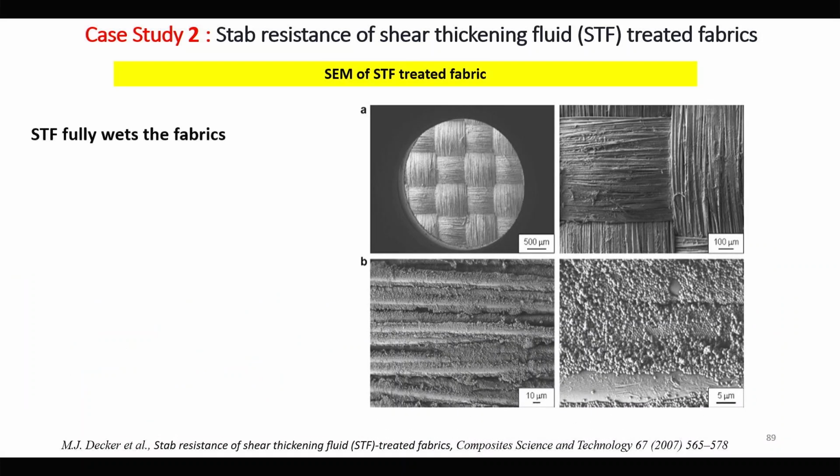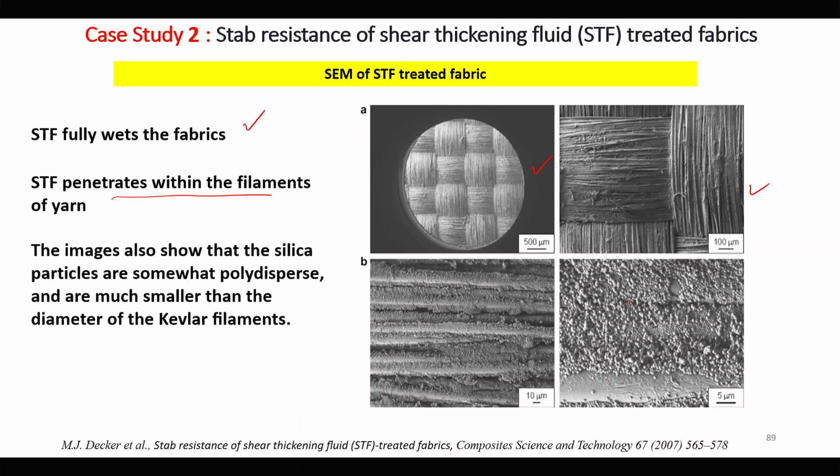Now, this is the scanning electron microscope picture. STF fully wets the fabric. So, there is a complete cover of STF material. STF penetrates within the filament yarn, so we can see that it is actually coating the filament also.